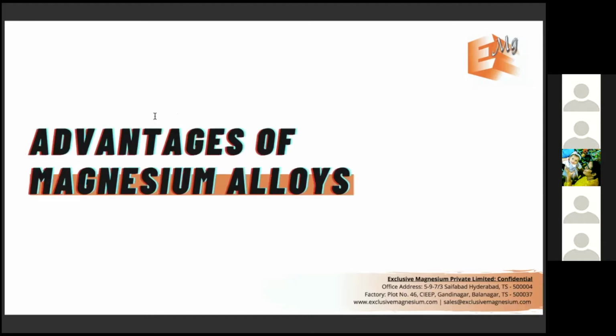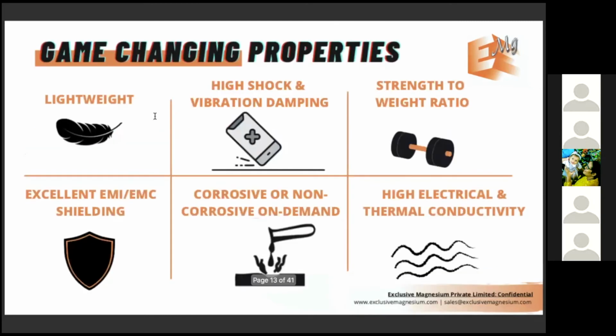Right. So we'll quickly move to the advantages of magnesium alloys. I'm sure you must have heard, even with basic research, that the main use case of magnesium is lightweighting, right? The reason lightweighting is important is because the density of magnesium is significantly lower. It is 33% lighter than aluminum and almost 75% lighter than steel. That's one of the major primary reasons people consider magnesium. The second major property that customers are interested in is the high damping and shock damping capability of magnesium. Not only will it prevent damage to the equipment when it drops to the floor or during a crash, it's used in almost every vibration damping equipment.